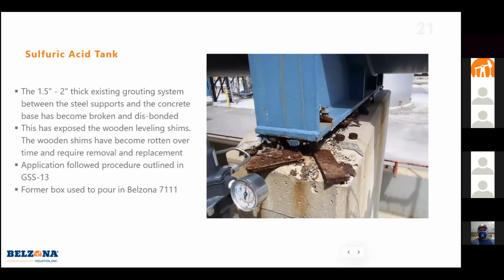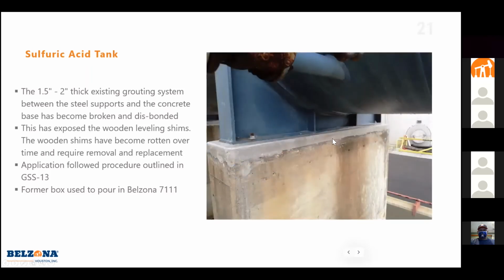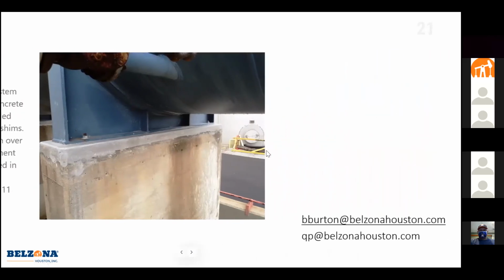Finally, one more secondary containment application, this time using our precise alignment. They had this tank base, a tank support sitting on the concrete support here. They were having some issues with the wooden shims rotting over time. So they went ahead and used a former and poured in the Belzona 7111, which you can see here. They poured it in about 1 to 2 inches thick and created a nice ground for this tank to sit on here. And all done in place.